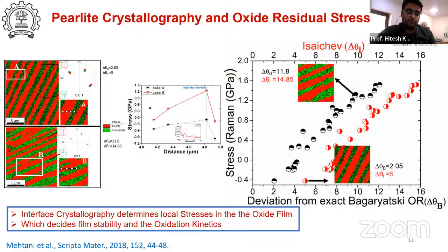We calculated the Raman stresses in a line by line intercept method. First, for the oxide forming on the ferrite, we calculated the Raman stress on that ferrite phase, then the cementite phase. But we observed that near the interface there is a certain enhancement in the hydrostatic stresses forming on the oxide scale.